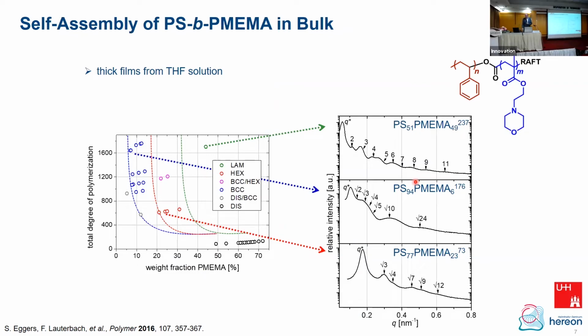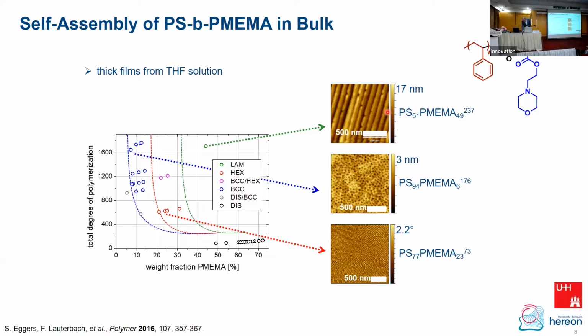And so this is a simplified phase diagram of a diblock copolymer, very roughly drawn, and the circles show the different polymers which were synthesized, and the colors somehow correspond nicely to the expected morphologies. Also the small angle X-ray scattering confirms these results. So here it's maybe more simple, AFM images of different structures. So we get lamellae, cylinders, and spheres. So everything is okay. Concerning the nomenclature, I should mention that these lowercase numbers indicate the weight percentage of the respective block, and this uppercase number at the end is the total molecular weight in kilodalton. So it's a simple non-IUPAC nomenclature.